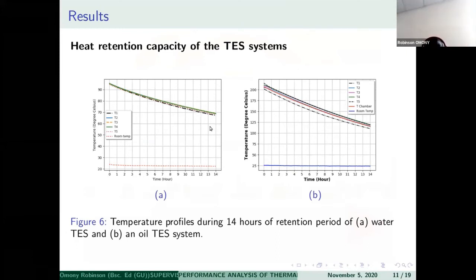the period of heat retention, the temperatures were measured, and for water, we found the storage at a temperature of 68, and that of oil was charged to 200 initially. After the heat retention period of 14 hours, we were able to get an average temperature of 108, and this temperature is high enough for cooking, say the following day before charging could start.